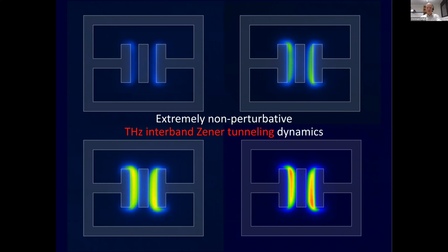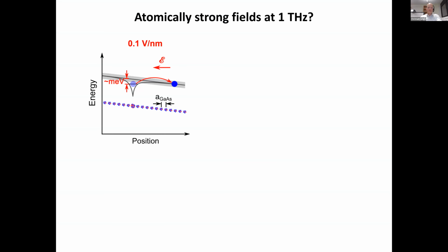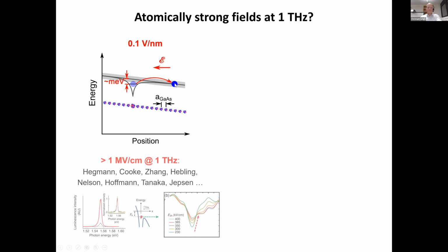So this is already showing these terahertz resonators. This is actually a near-infrared or an optical image of those resonators under illumination with the terahertz field, and how these come about, I will explain in a second. So the idea is here to apply a very strong field to a semiconductor. If that field is on the order of a megavolt per centimeter, that's 0.1 volts per nanometer, it certainly is enough to drive ionization of shallow donor states, for example, in the material.